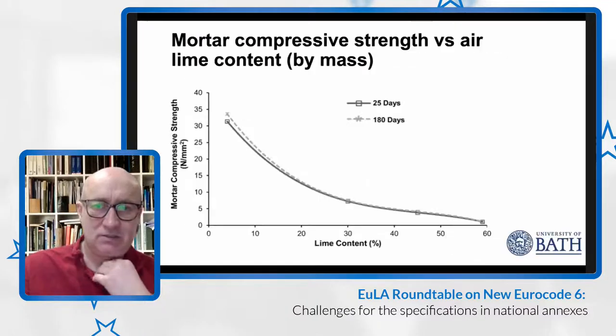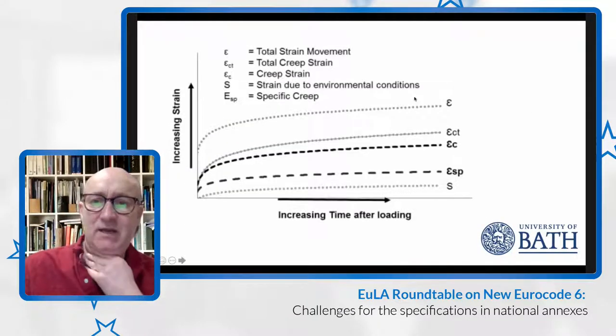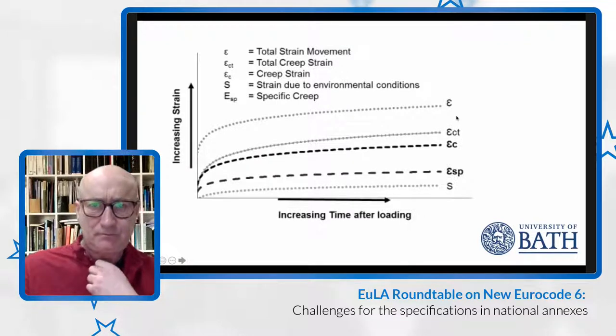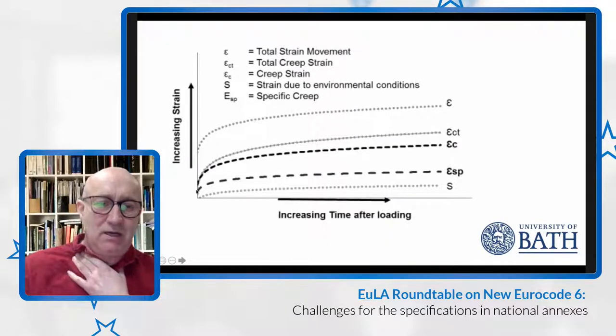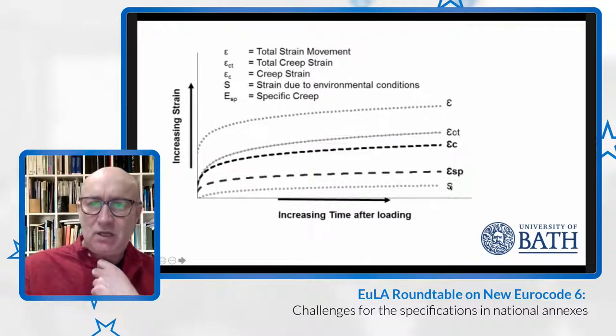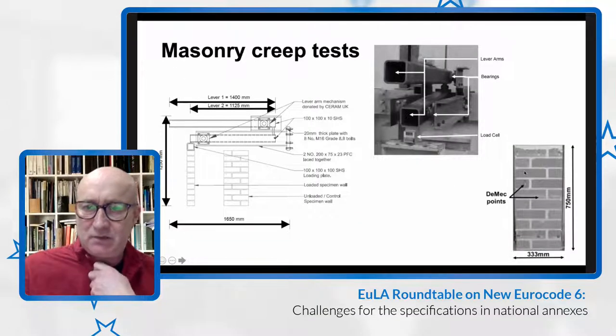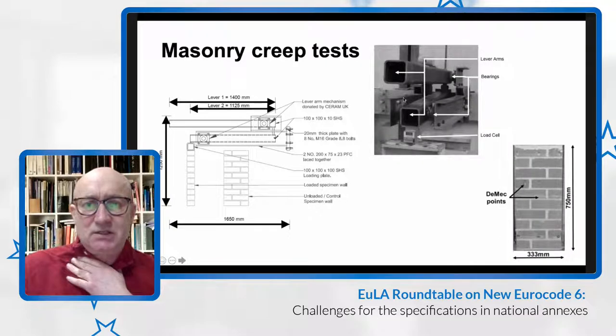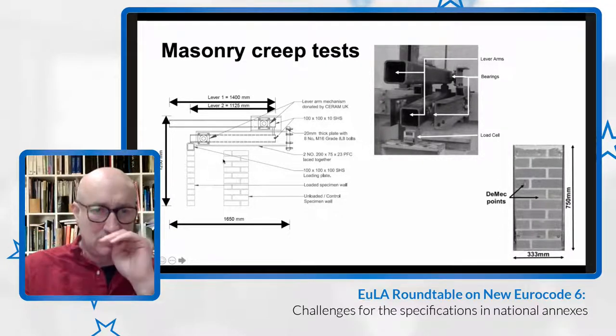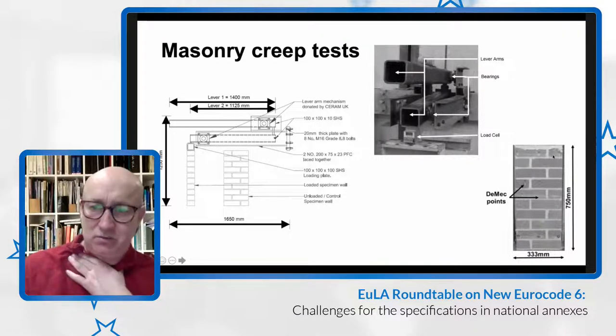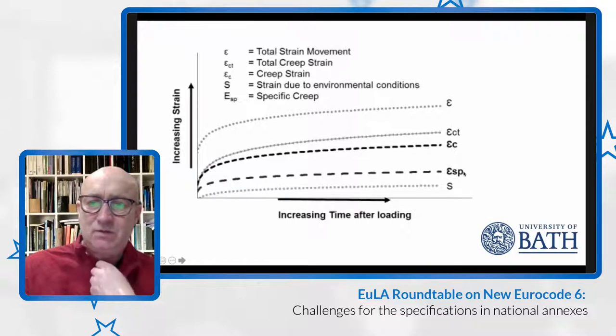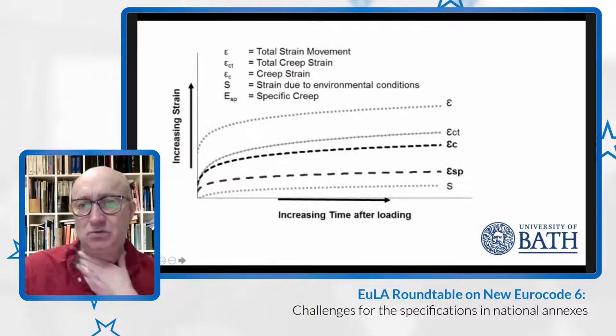And then, to just go through this graph again, what we measured on the specimens is this top line here, and then we deducted the initial elastic strain that we measured when the load was applied. And then we also measured, and you can't see, but together with all of the experimental walls in here, we had an unloaded specimen, which also had the strain gauges on as well. So we measured the strain due to primarily shrinkage as the walls dried out.